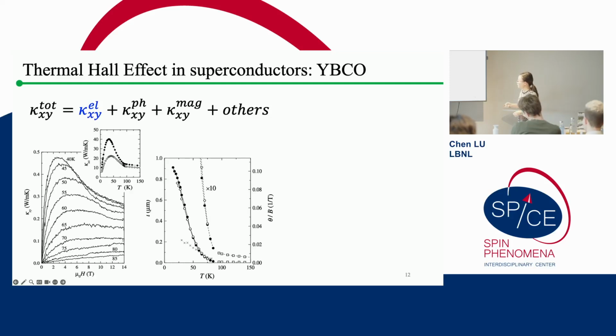So I give you one example, which is this picture. The left-hand side figure shows the thermal Hall conductivity versus field that has been measured in this YBCO, which is a high-temperature cuprate superconductor. So for this YBCO at this particular doping, you can see the TC is around 60 to 70K, and the figure in the middle is basically the thermal conductivity versus temperature.